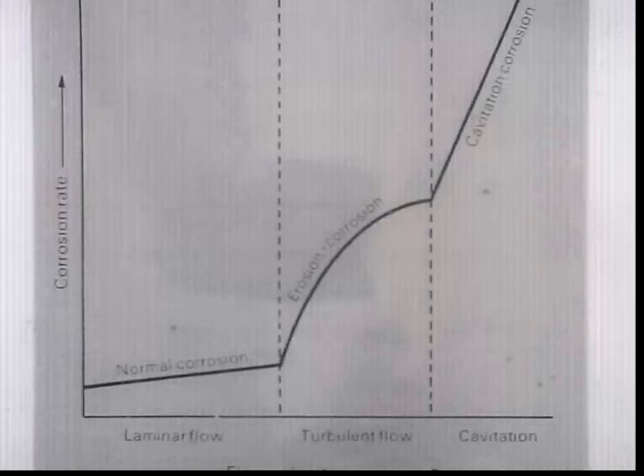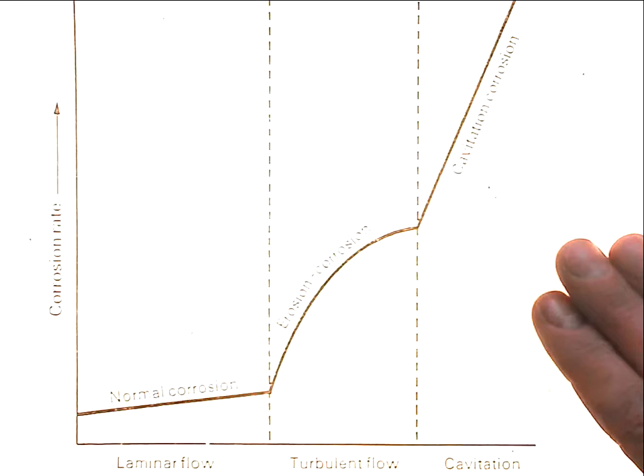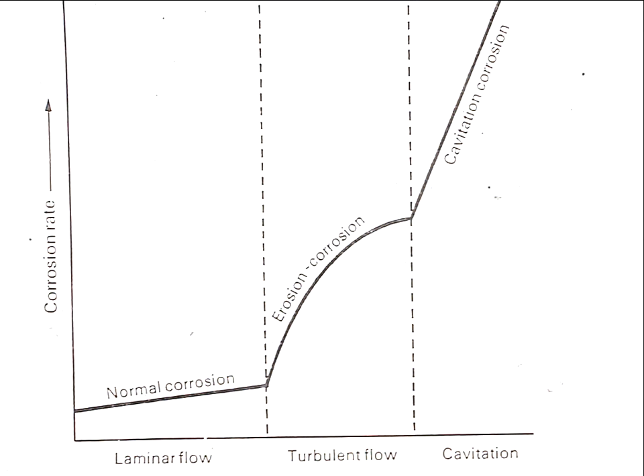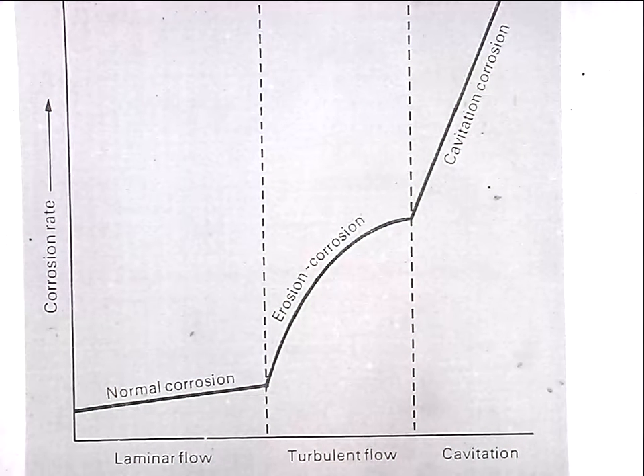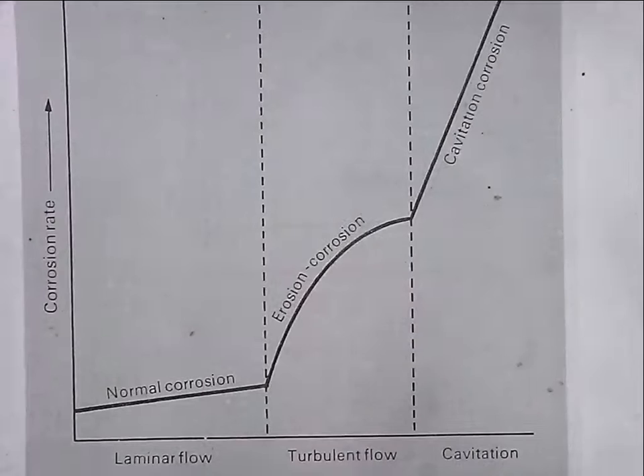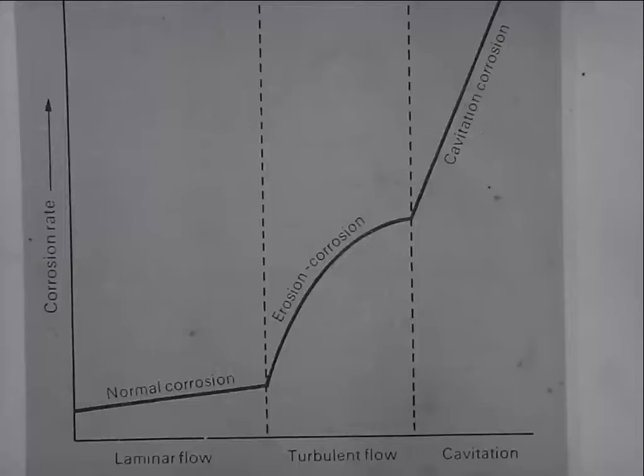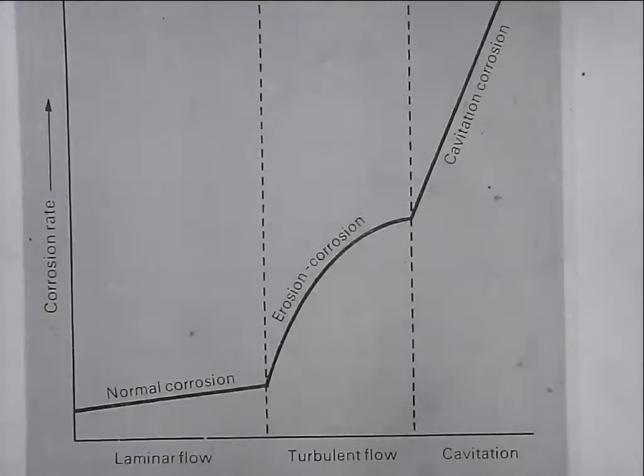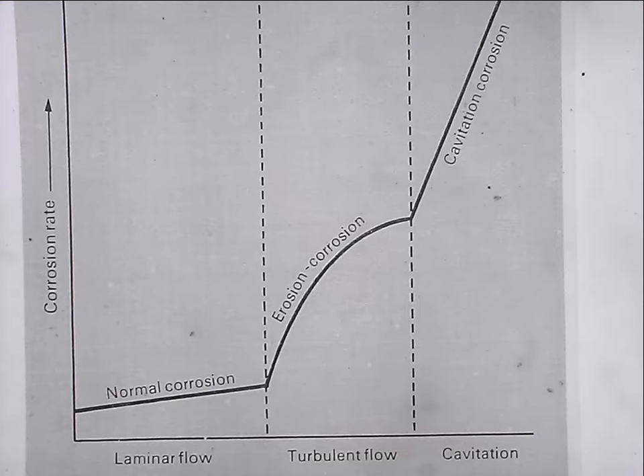Okay, so again it's corrosion rate, but this time not just the laminar flow region. We've added turbulent flow, in other words the velocity getting even higher, and then finally cavitation. And what you find is that under laminar flow conditions the corrosion rate increases gradually, and then once you go to turbulent flow the corrosion rate increases rather more significantly. And then when you go to cavitation, the damage becomes accelerating very rapidly.